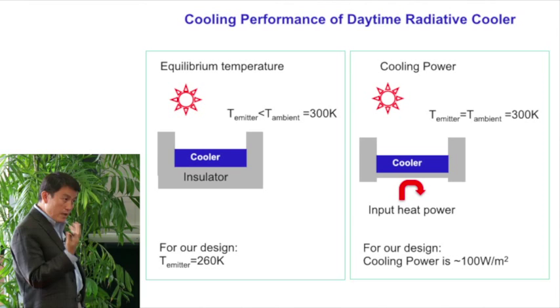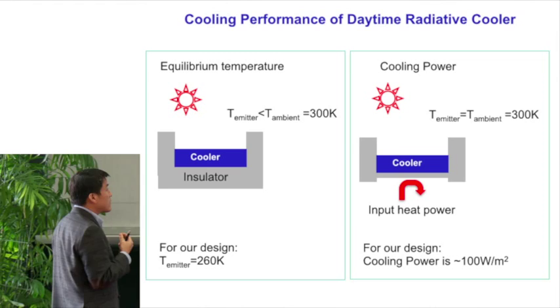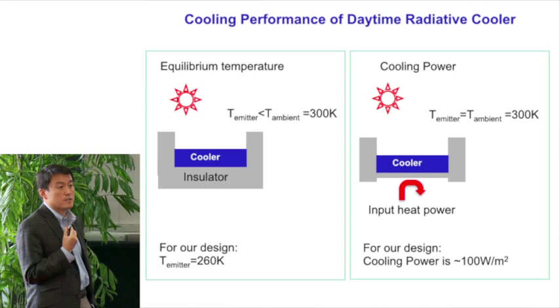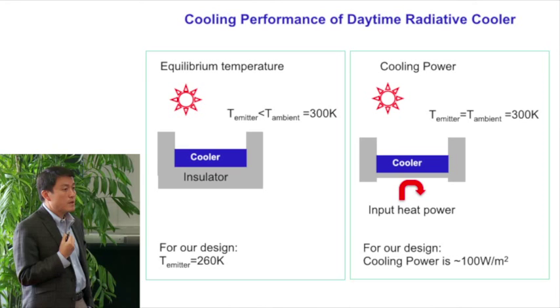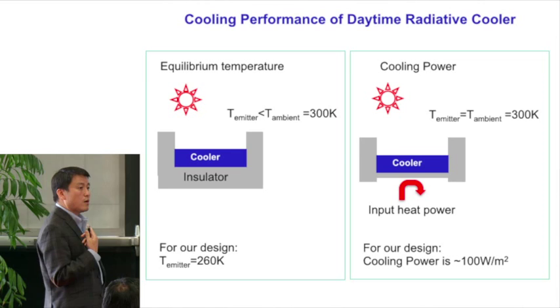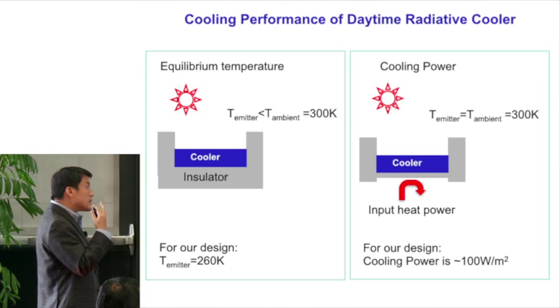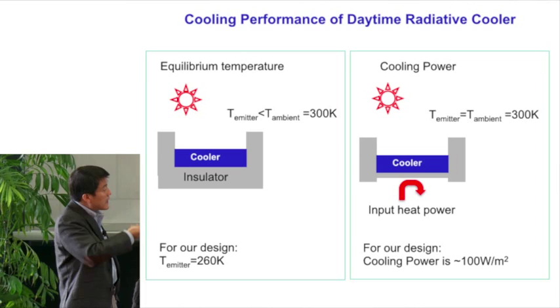In other words, on a hot summer day at noon, there is a potential that you can get ice out of this in an entirely passive way, without using any electricity. And that's a very unusual potential for the future. Alternatively, because this thing has a temperature lower than the ambient, you can put a heat load in there. As you put a heat load in, its temperature is going to rise. And you can ask, how much heat load can I put in to drive its temperature back to the ambient air temperature? That number turned out to be, theoretically, on the order of about 100 watts per meter squared.